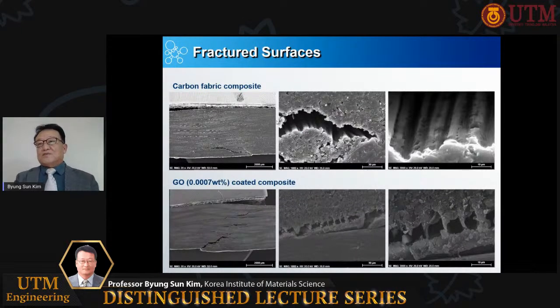The same morphologies on the fracture surfaces of carbon fabric on top and graphene coated carbon fabric composites are shown at the bottom. In the carbon fabric composite on top, it can be seen that the cracks have propagated following the resin-rich interface between the fabric and the matrix. In the graphene oxide coated carbon fabric composite shown at the bottom, the cracks have propagated through the thickness, explaining the improvement in the short beam strength.